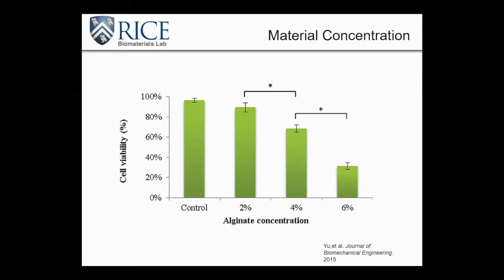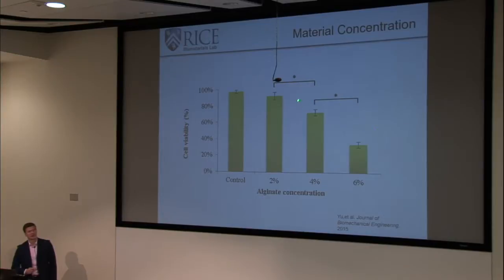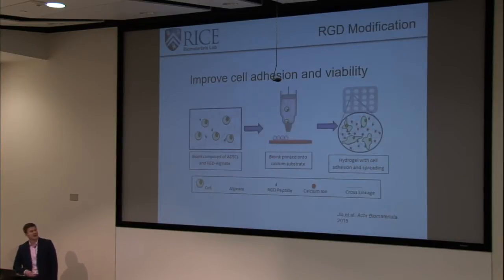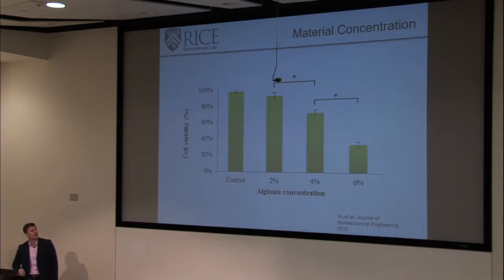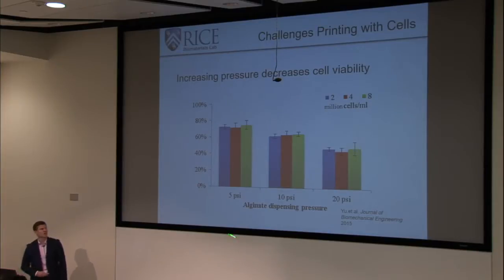So this is one of those challenges where when you're trying to print with the bioink for the first time, you'll often tend to go towards a higher concentration because you have higher viscosity, you have better cross-linking potential, you have better structural integrity, you have a product that usually, like I said, gels faster, so you don't have this spreading effect of your bioink. But by doing that, you sacrifice the viability of your cells extremely quickly. And in fact, the biggest determinants of cell viability in extrusion printing methodologies often comes down to the concentration of cells that you're using in your bioink, as well as the dispensing pressure that you're using on your bioink.